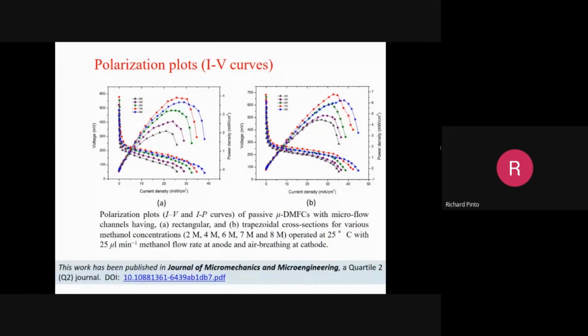Now, let us go into some of the performance characterization. This was published in the Journal of Micromechanics and Microengineering, two years ago. And you see here, these are called polarization plots. The left side is a voltage versus current density plot, and the right side is power density as a function of current density. The open circuit voltage is high, though you don't get the theoretical value mentioned in the earlier equation.